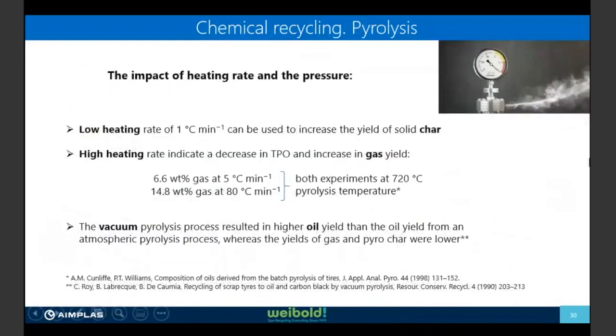Okay, this one. So the impact of the heating rate and the pressure is this one. A low heating rate of 1 degree per minute can be used to increase the yield of solid char. High heating rate indicates a decrease in TPO and an increase in gas yield. As you can see there, for a pyrolysis temperature of 720 degrees, you can achieve up 5 degrees per minute, 6.6% of gas.